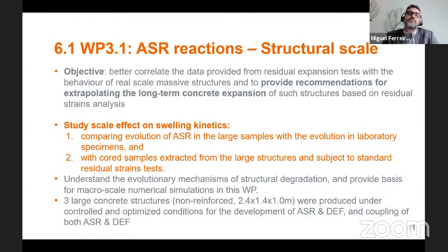Very large scale concrete blocks, non-reinforced, were produced. The dimensions are 2.4 by 1.4 by 1 meters. And these were produced under controlled and optimized conditions. And then they were developed to look at specific expansion internal swelling reactions. One is ASR, the other is delayed Ettringite formation, and also the coupling of both of these. So at the same time having ASR and delayed Ettringite formation, hence the 3 blocks. And experimental protocols to accelerate the ASR or the delayed Ettringite formation were developed, depending on the different mechanisms. And these would allow for us to better observe the expansion reactions in the structural scale. So this that I've described now has actually been all the work of the PhD thesis of the work package leader Jacques Jabour at IRSN.